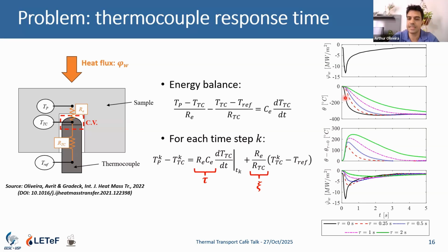If I use these thermocouple responses in my inverse method that I showed you, I'm going to have very bad estimates for the boundary heat flux. So we need to use large thermocouples in industrial conditions, because if we use very small wire solder thermocouples, they are going to break for sure with the thermal shock.